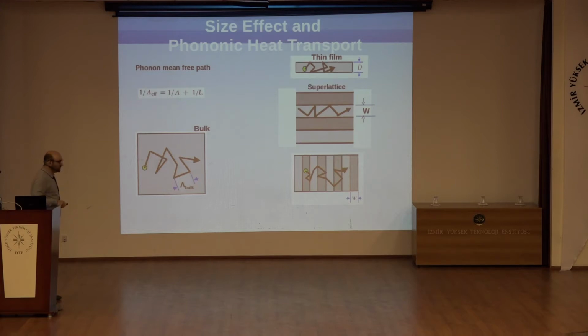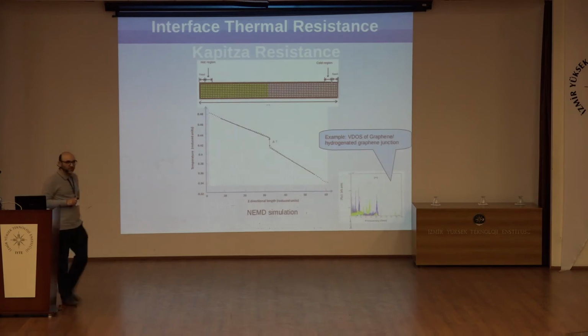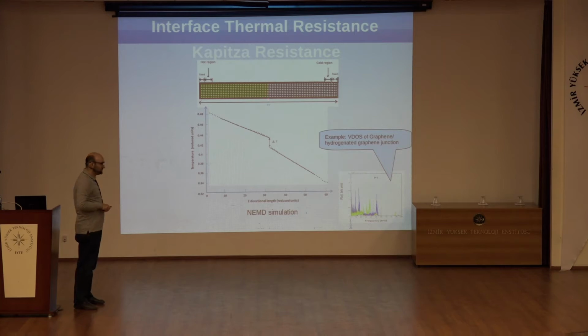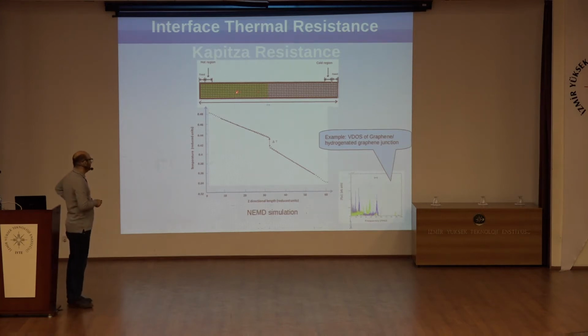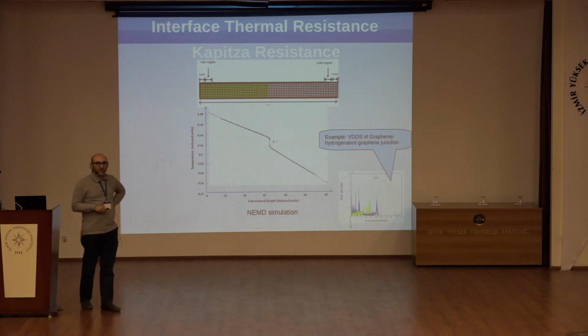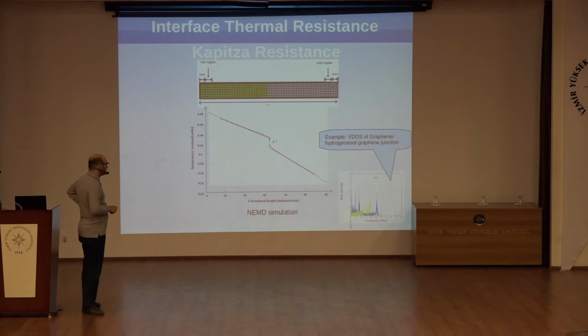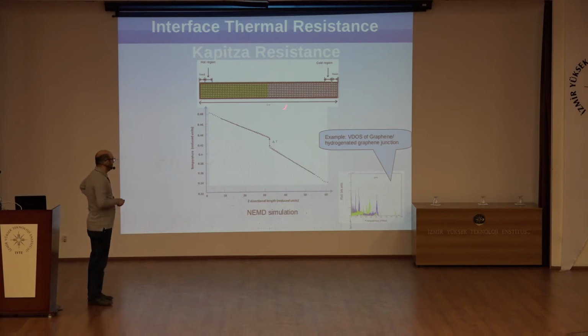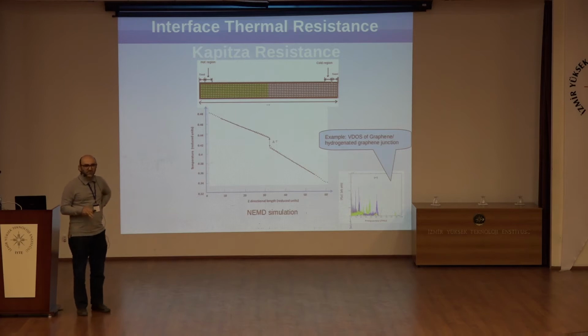When we come into lower dimensions, there is some sort of scattering that has been described by Professor Shiga, suppressing the mean free path of phonons. And also there is something else in between. When we have an interface in a system, for instance two perfectly matched lattices, just by changing the mass of the lattice on the two sides of the system, it might be possible to get something called Kapitza resistance. And it is common for low-dimensional systems